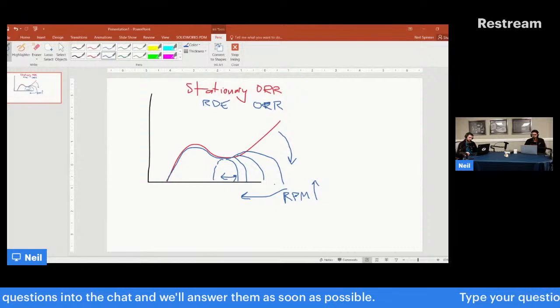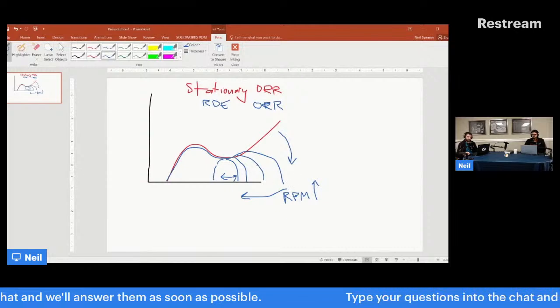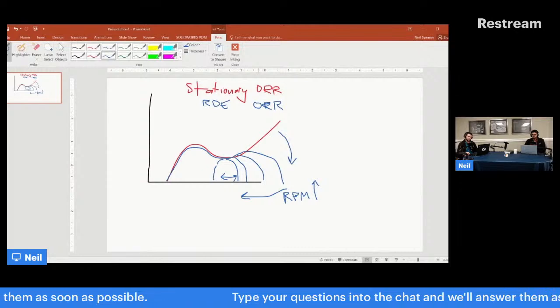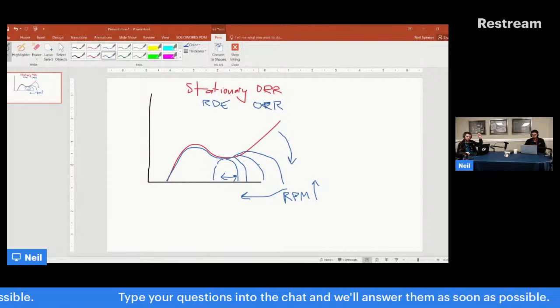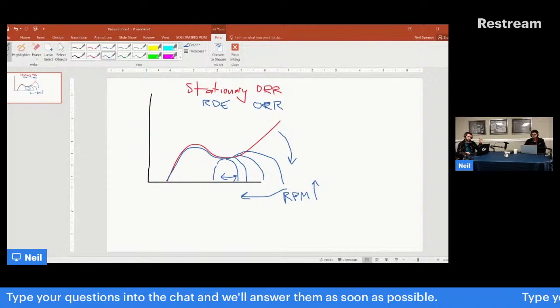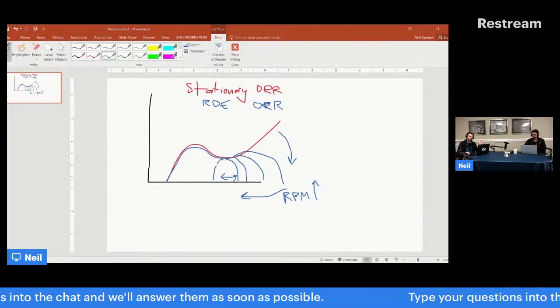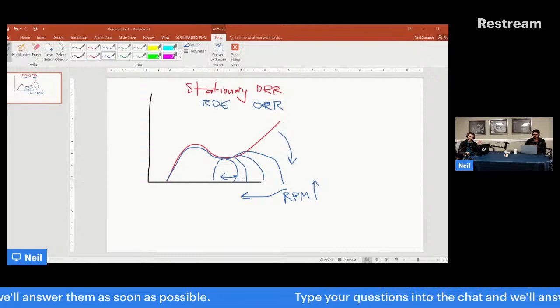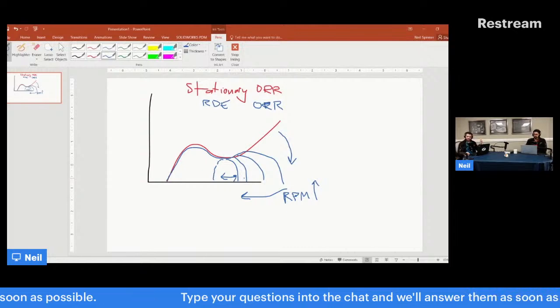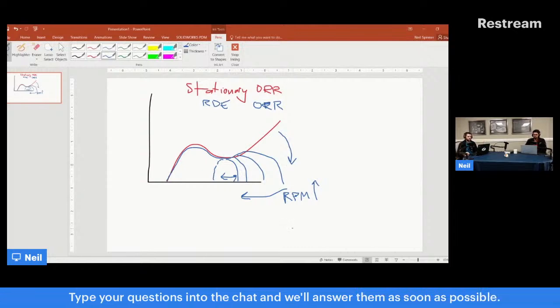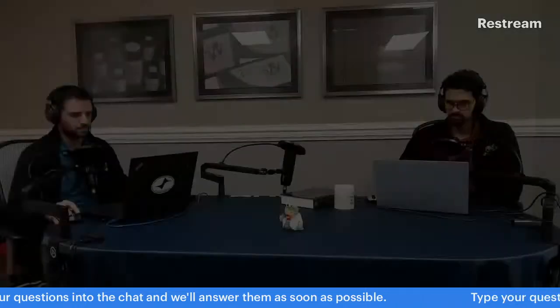It gets smaller as the RPM gets higher because it's directly proportionate to the diffusion layer thickness. As you rotate faster, the diffusion layer thickness shrinks, which means the width of the semicircle gets smaller. There's lower resistance because the diffusion layer thickness is smaller. Stuff gets to the electrode quicker. That's why you get higher current. So clarify if that isn't what you were asking. I think that's what you were asking, and that's the answer.